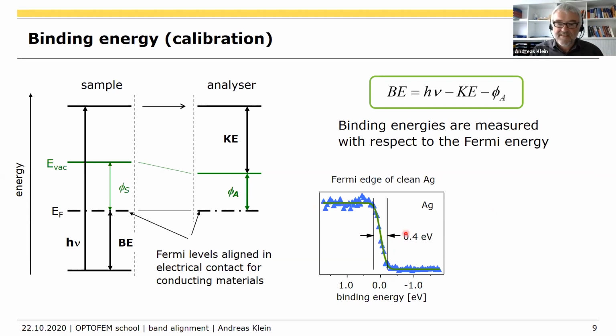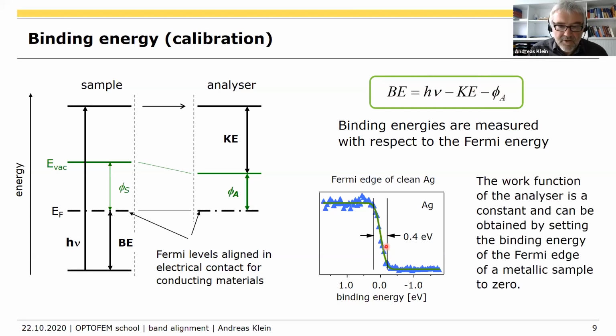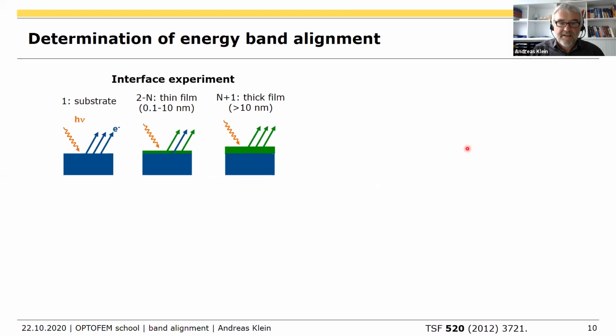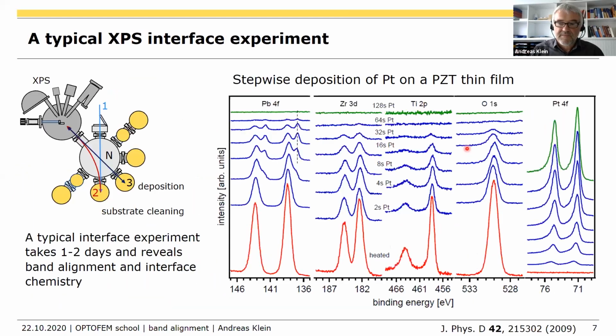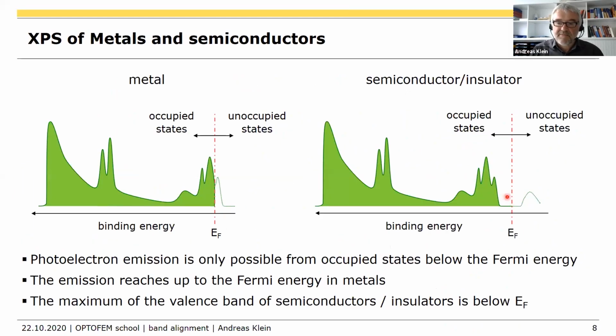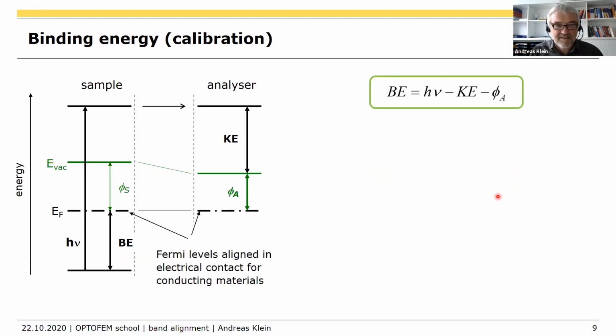Okay, so now by measuring this Fermi edge, we can adjust this because we know that the binding energy here should be 0. This is what we measure, this is what we know, and we set the binding energy to 0 by just calibrating this value with this measurement. Okay, so that's a good thing. So that means we can measure the binding energies with respect to the Fermi energy. And if we now go back to the semiconductor, you see that this quantity is something which we can quantitatively measure with our technique with an accuracy of, let's say, typically 50 to 100 milli-electron volts. It's not perfect, but it's still a pretty good number.